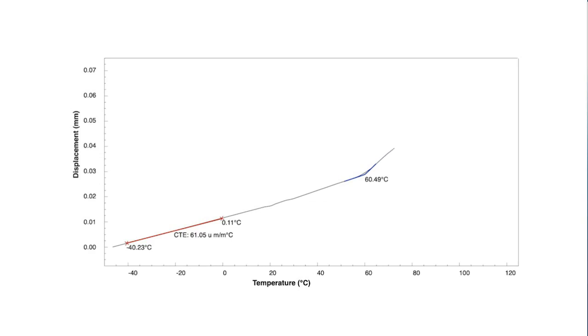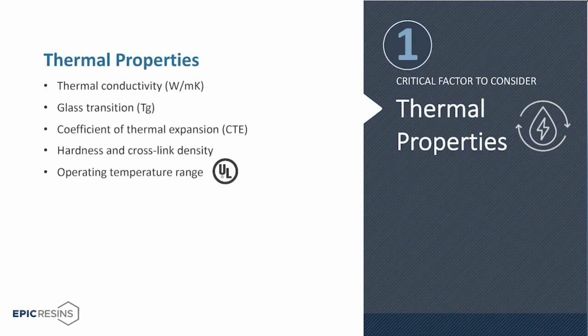Continuing to move up the temperature to the right of the graph, you see another slope. This is the post-TG CTE, which is higher than the pre-TG CTE. It is important to understand where the TG of the polymer is relative to your operating temperature range to reduce component stresses that occur during this thermal transition. A fourth property is cross-link density and hardness.